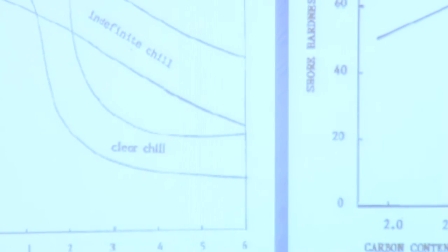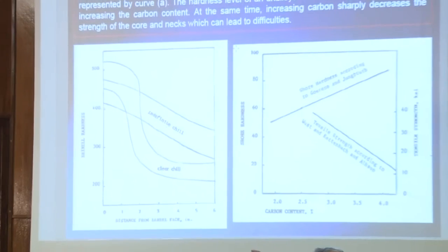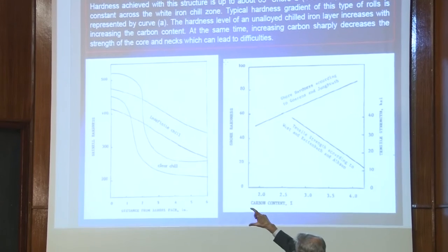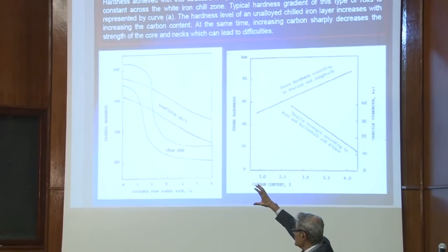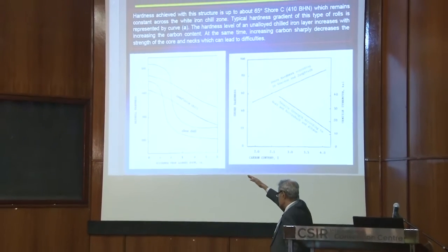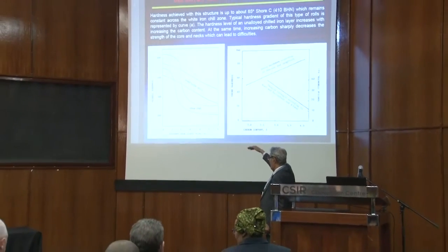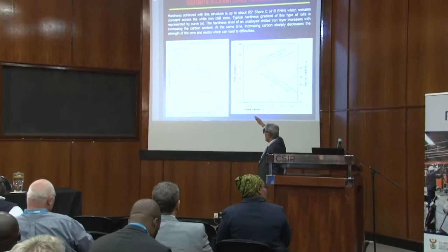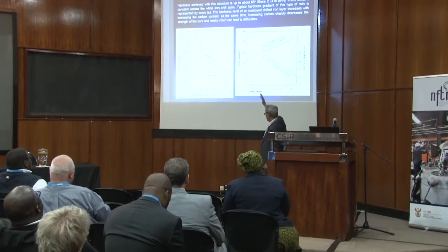We have so many different types of rolls, about 50 or 60 different rolls, but mainly they can be categorized in two groups: definite chill or clear chill rolls and indefinite chill rolls. In this hardness gradient of the clear chill, this is the distance from the surface of the barrel, and this is the hardness. You have a layer of clear increase in hardness in the clear chill, and then you have a sudden drop in hardness until the center of the roll. In the indefinite chill, you have a gradual decrease in hardness between the roll surface and the roll center.